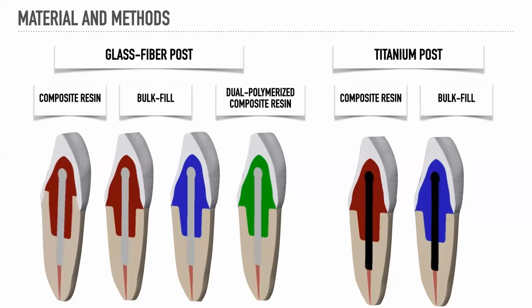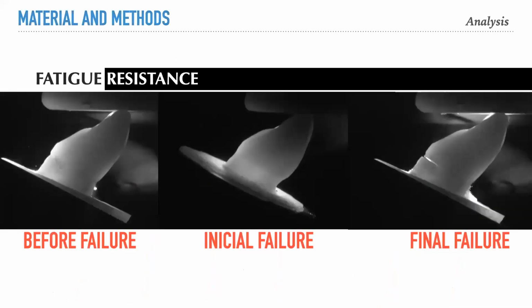So all these samples received the same preparation and the same treatment as the previous study. And then as we knew about the initial failure, we evaluated these samples before failure, with initial failure, and with final failure. Now I will show you another movie with the before, initial, and final failure. Here we can see the final failure and the wide gap opening between the crown and root. So all the samples were evaluated using the initial and final failure.